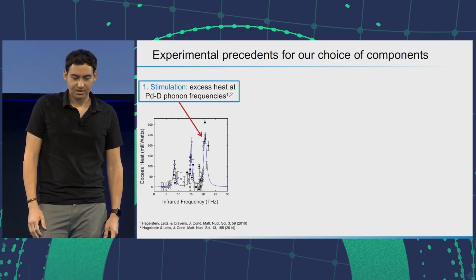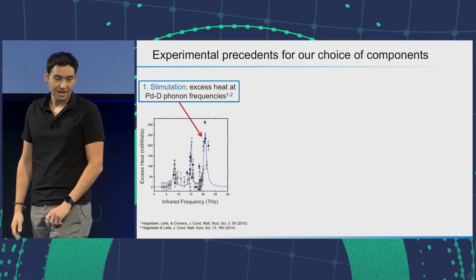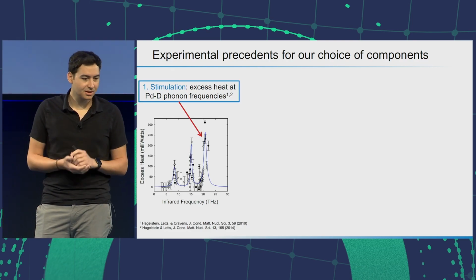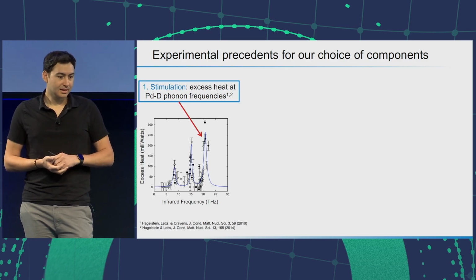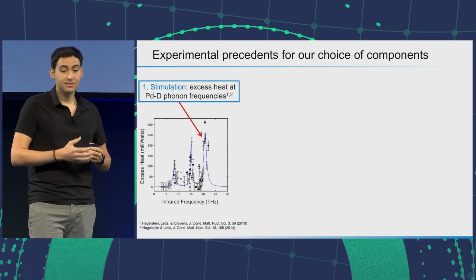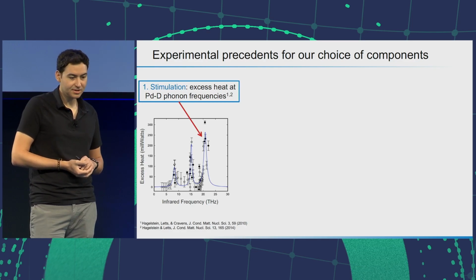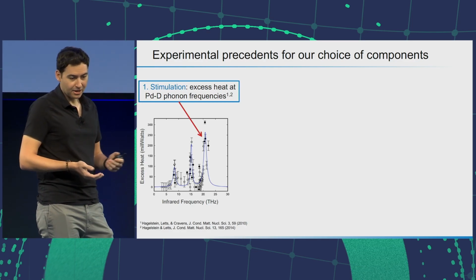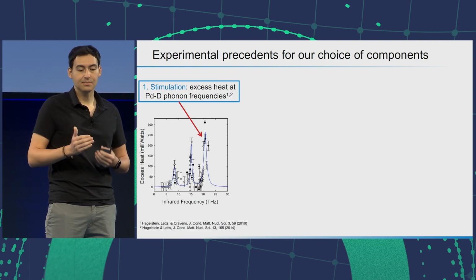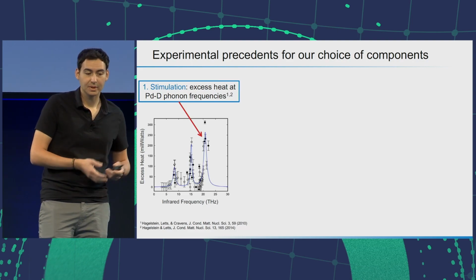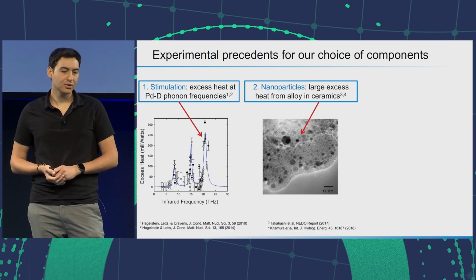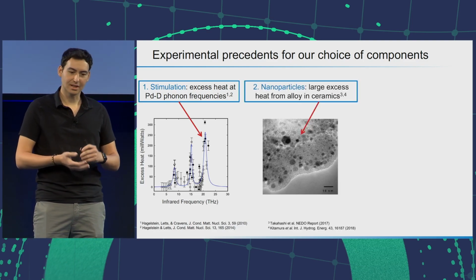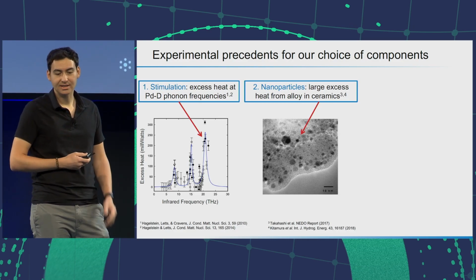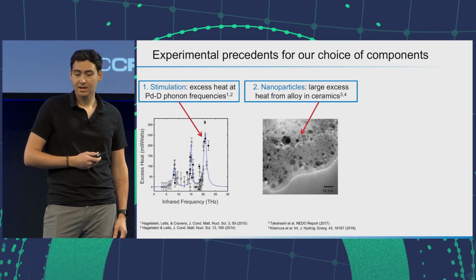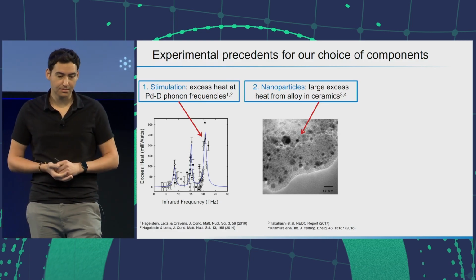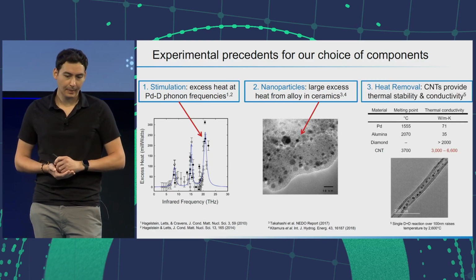And so it turns out there's some experimental precedents for these ideas. We're not the first to think of stimulation. This was also mentioned in the previous session. Here's a plot of excess heat as a function of infrared beat frequency. This is work from Hagelstein, Letts, and Cravens. And they show there's an apparent enhancement of excess heat at frequencies that appear to line up with the phonons of palladium deuteride. So that's the stimulation component. Second is nanoparticles. Again, we're not the first to think of nanoparticles. There's been large excess heat reported in alloys. Here they're coupled to ceramics. This is work from Japanese groups, the NEDO Report.